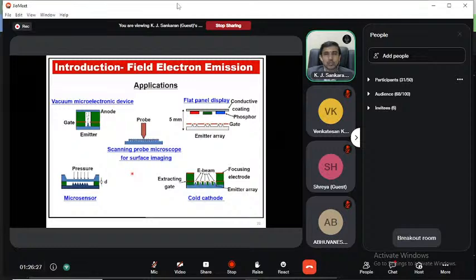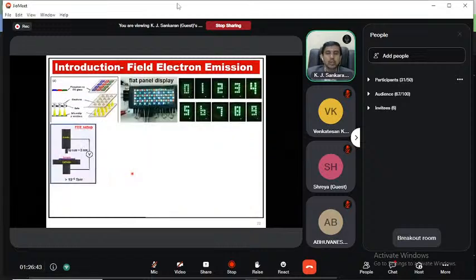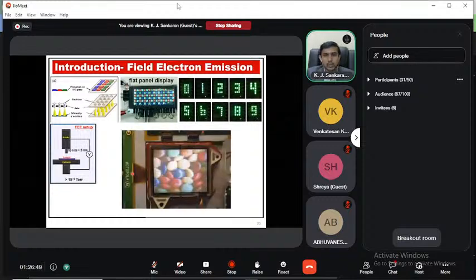Where can we use these field electron emission based materials? The applications are as a cathode in vacuum microelectronic devices, flat panel displays, microsensors, cold cathodes, and recently we can coat them on AFM tips to make scanning probe microscopy for surface imaging. This is one of the field electron emission devices developed by Motorola, a flat panel display. But apart from flat panel displays, there are several applications coming, such as X-ray imaging. A Korean group is working on X-ray imaging using field electron emission based devices, and we can also generate a plasma, which we are focusing on as a plasma illumination device.